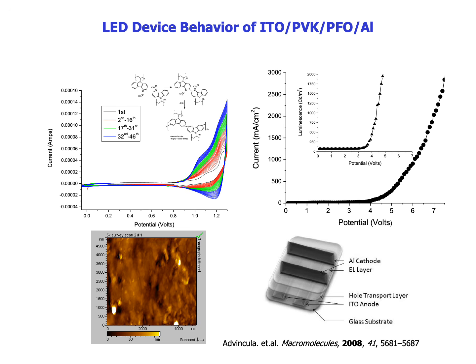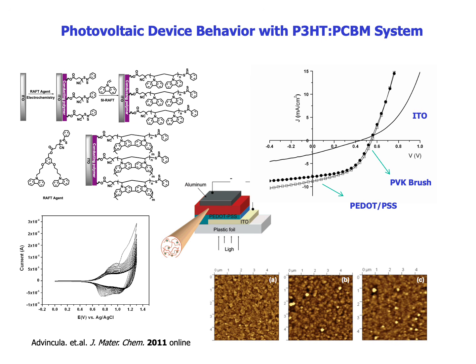a native ITO. By inverting the function, we can then use this configuration where the polythiophene PCBM is your active layer. In this case, in comparison to PEDOT:PSS, the PVK brush can then serve as an important layer to facilitate photovoltaic device performance. So in this case, the efficient device was shown in this bulk heterojunction type of system where the smooth curves in the film as well as the electrochemical cross-linking resulted in performance, if not the same or better than PEDOT:PSS.